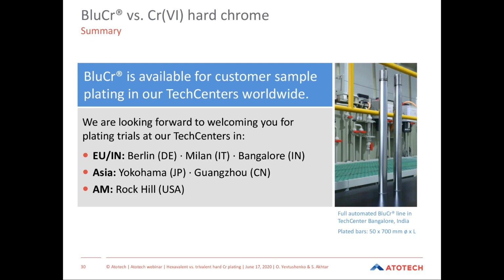But if in your application corrosion resistance is not the major requirement and wear resistance is much more critical, then you could probably reduce the nickel thickness down to maybe 5 microns and put a slightly thicker blue chrome layer on to handle the wear resistance. Alternatively, if corrosion resistance is the main priority, then of course we would recommend that you plate maybe 10 to 15 microns of nickel, followed by 5 to 10 microns of blue chrome, for example. So this really depends on the type of application and the type of environment that the finished parts will be subjected to.